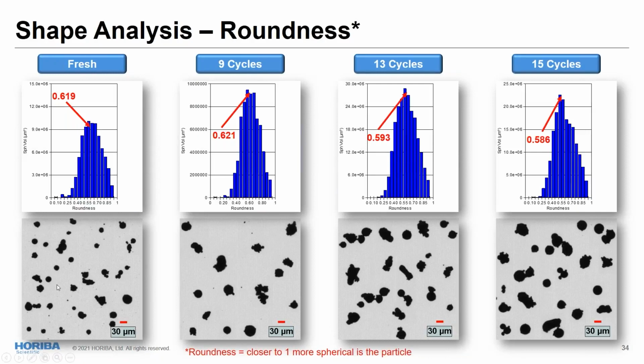We can see here the particles are almost free flowing. We have some stick-like particles that are non-spherical. The average roundness here is 0.619. And you can see a lot of very small particles. The scale here is 30 microns. So you can see we have a lot of small dots here, and most of the particles are free particles.